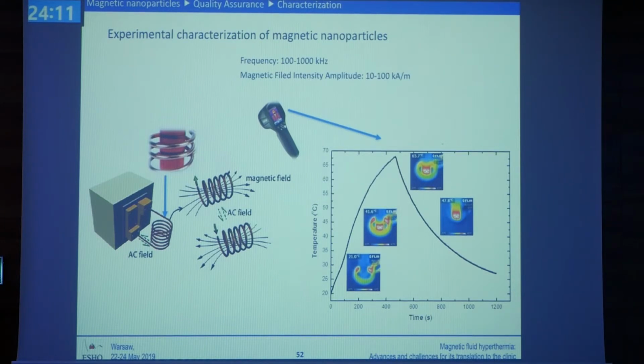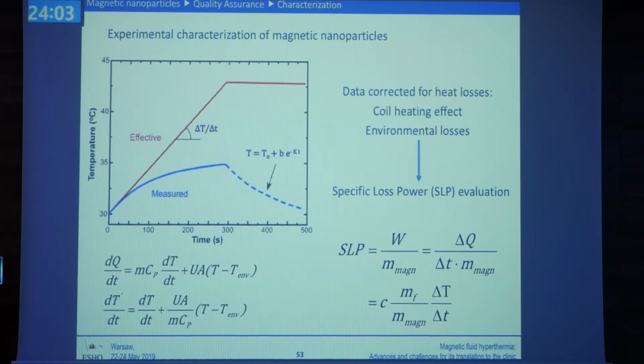And then we measure the temperature increase, then we turn off the current, and you can see the drop-off of the temperature. Why do we always measure? We always measure in the lab both the increase and the fall of the temperature. Why? Because, as the previous speaker showed for HIFU, that was very interesting, the way they control the heating, where they heat. Here you have the same idea.